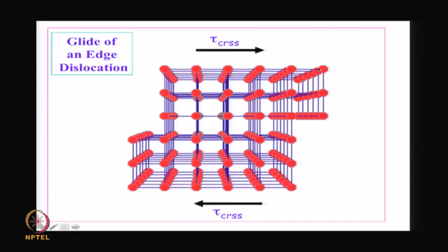You can see that because of the presence of this surface step here or in the beginning here, there is no internal distortion inside the crystal. So, these are not really dislocations in that sense, the half plane associated with dislocation, but only a surface step. So, to create this unit surface step, a dislocation has travelled through the entire slip plane and come out of the crystal.